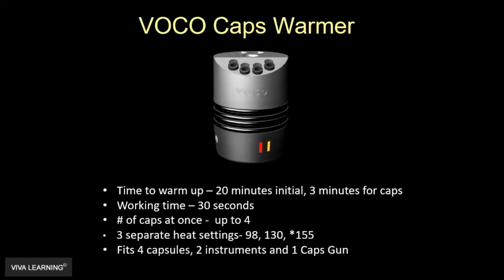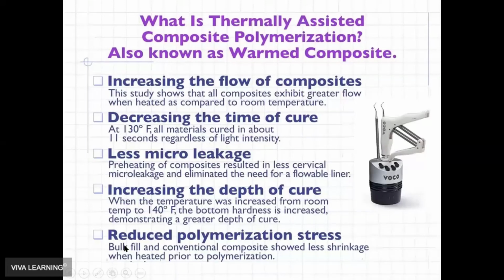There's different adjustments here. You can see, depends on the setting that you want. You can put 4 compules in at once for injection molding. You get about 30 seconds once you load this into your composite gun. You have to express the liquefied composite within 30 seconds, because otherwise it's going to cool down and the viscosity changes. So this is Voco's CAPS warmer.